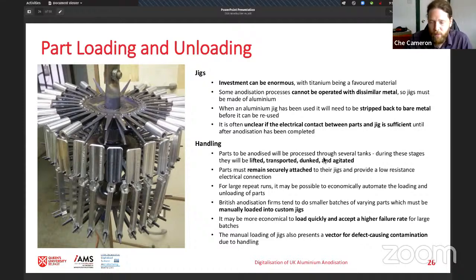Regardless of the type of material of the jig, one of the issues is you'll not often know if the electrical contact was good or not until right at the end of the process when you actually see the finished part and did it anodize correctly or not. So I mentioned that there's a lot of different stages to anodization, a lot of different tanks it has to go through basically for cleaning and etching, and the parts are loaded at the start of this, and then they go through all these tanks. They're being lifted, transported, dunked, the tanks are being agitated, and throughout all of that, the parts have to remain securely attached to the jigs, and not just that, it has to be a good quality electrical connection that those parts have.